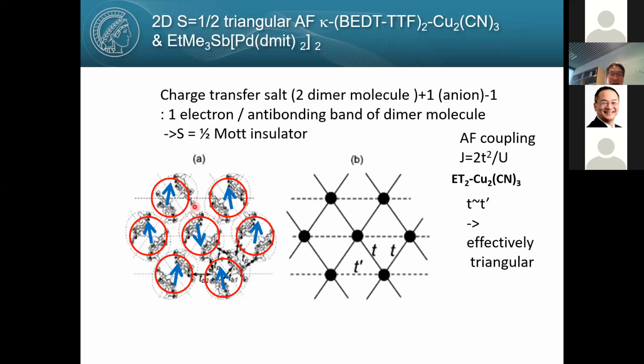Those dimer molecules form a lattice like this, forming layers. The anion wants to be minus 1, so it takes one electron from the dimer molecule. Originally there were two electrons in the antibonding band, but the anion takes one electron from the antibonding band. As a result, each dimer molecule has one electron in the antibonding band. Since the overlap between molecules is relatively small, they form an S equal 1/2 Mott insulator, with one S equal 1/2 moment on top of each dimer molecule. That's why these organics are S equal 1/2 magnets.